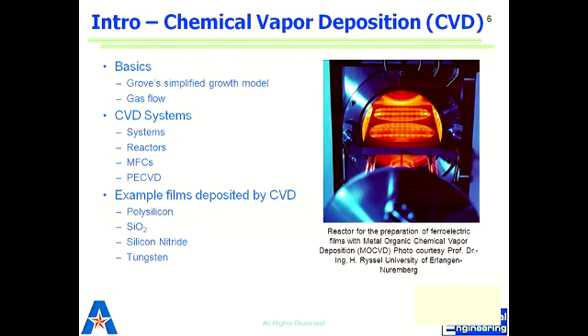So that's PVD. CVD is a simple growth model. We flow things in there and we let them react. We get the material deposited and then we get our film. It depends on whether it is a temperature-driven reaction or an energy-driven reaction. In one case we are using heat to provide energy for the reaction. In another case, we would use plasma at lower temperature to provide energy for the reaction. In the case of temperature, it would be called LPCVD. In the case of direct electrical energy, it's called PECVD, plasma enhanced CVD. They both have their own pluses and minuses.